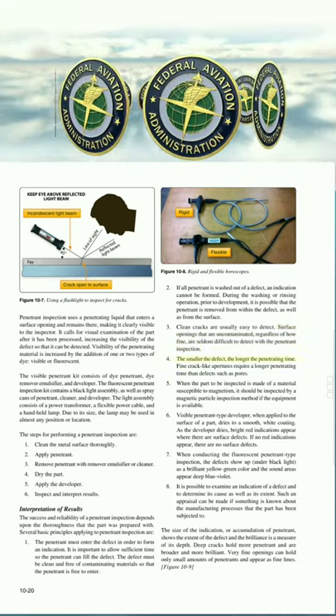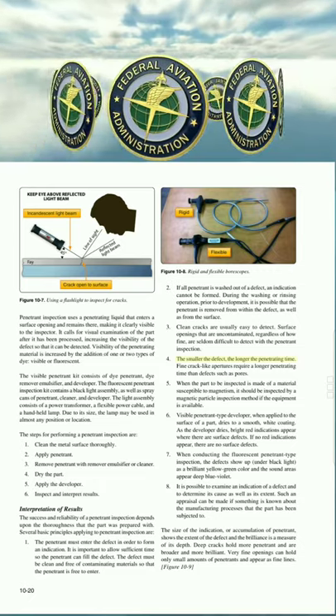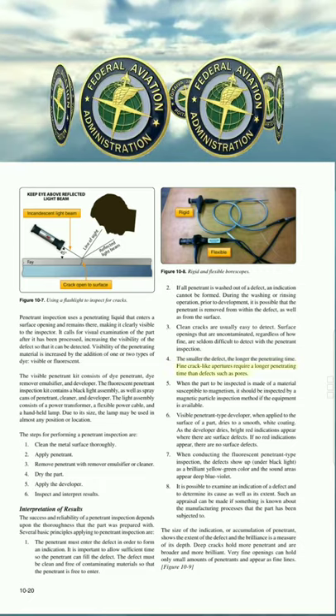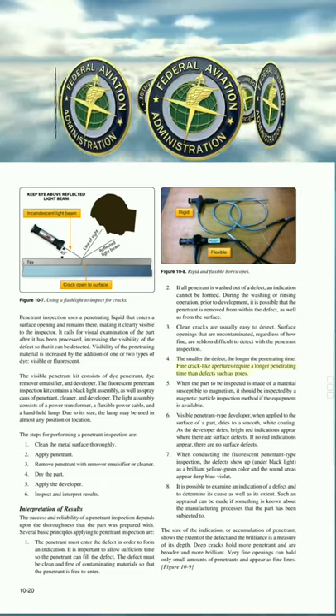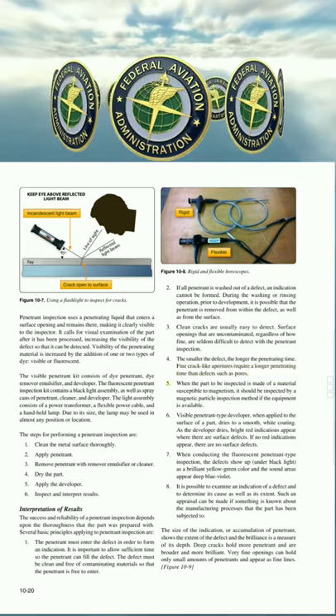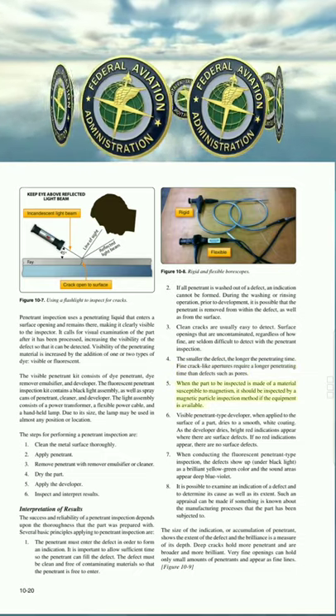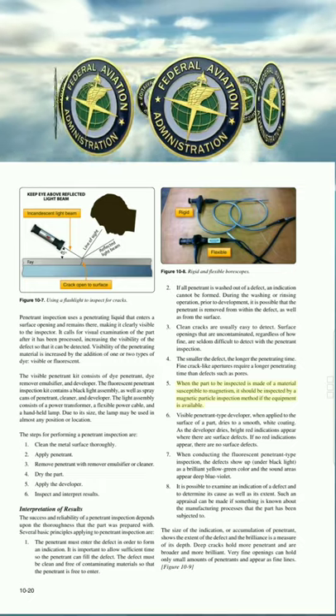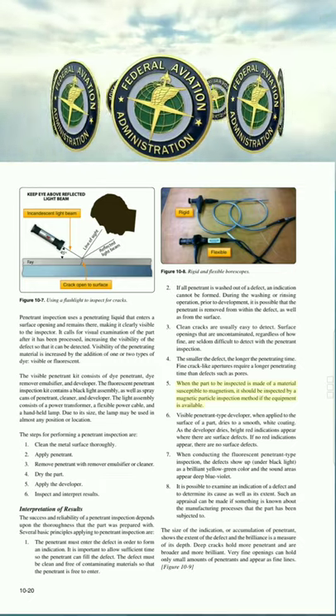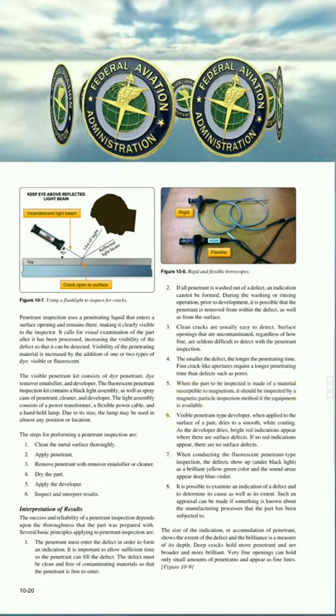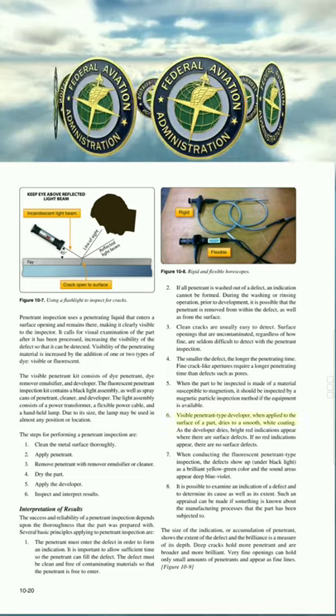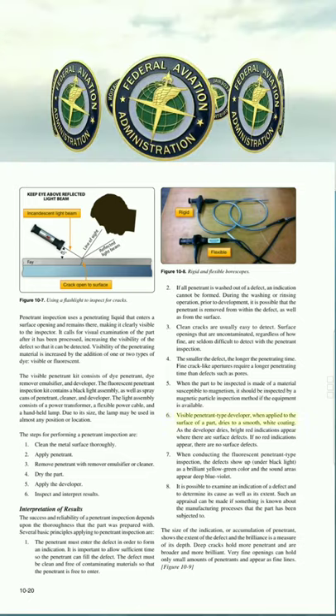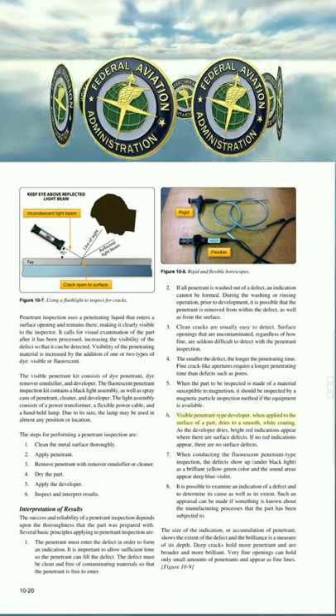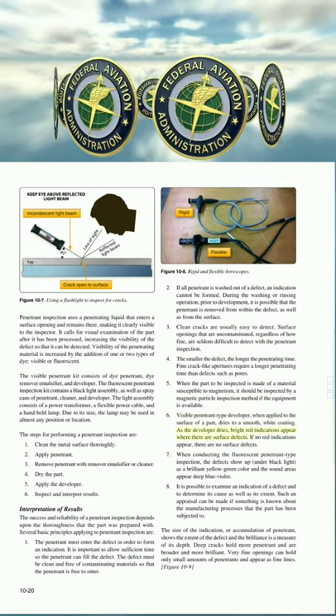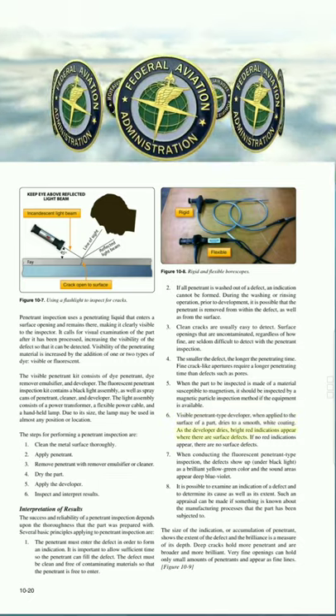4. The smaller the defect, the longer the penetrating time. Fine crack-like apertures require a longer penetrating time than defects such as pores. 5. When the part to be inspected is made of a material susceptible to magnetism, it should be inspected by a magnetic particle inspection method, if the equipment is available. 6. Visible penetrant type developer, when applied to the surface of a part, dries to a smooth, white coating. As the developer dries, bright red indications appear where there are surface defects.